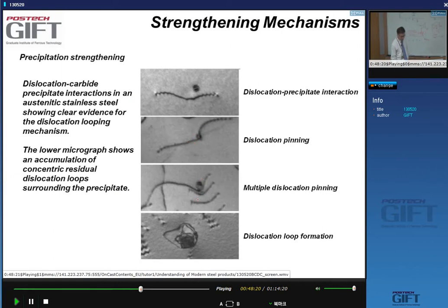You can see here the buildup of dislocations at the particle. And when a few of these dislocations have passed this type of particle, you can see they're surrounded with dislocation loops.